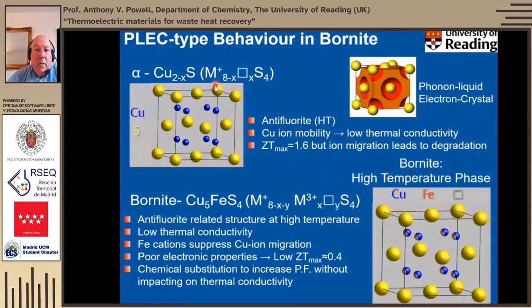The difference now, this would be the end member here without any copper deficiency, would be M8S4. This is M6S4. So that means there are 2 vacancies per formula unit. And those are distributed at a high temperature. The vacancies, the copper and the iron ions are distributed randomly over tetrahedral sites in the anti-fluorite type structure at high temperatures. It has a low thermal conductivity, and in principle, we think that the iron cations are going to suppress that copper ion migration, but unfortunately, the electronic properties are low, and we get a ZT of only 0.4.